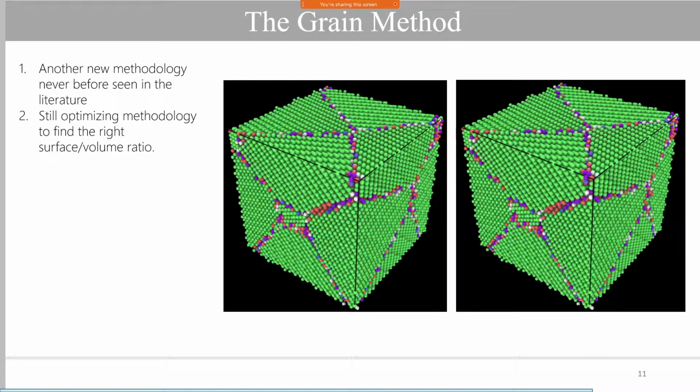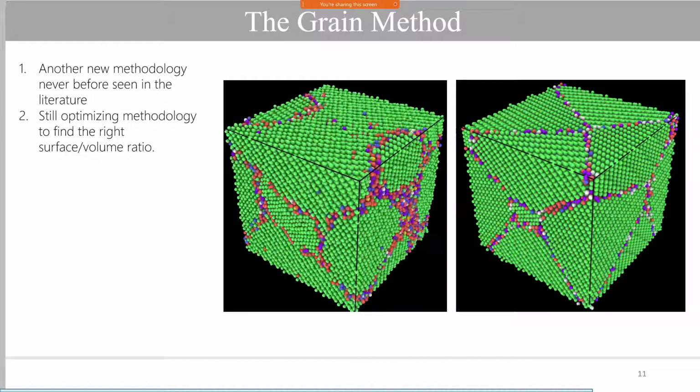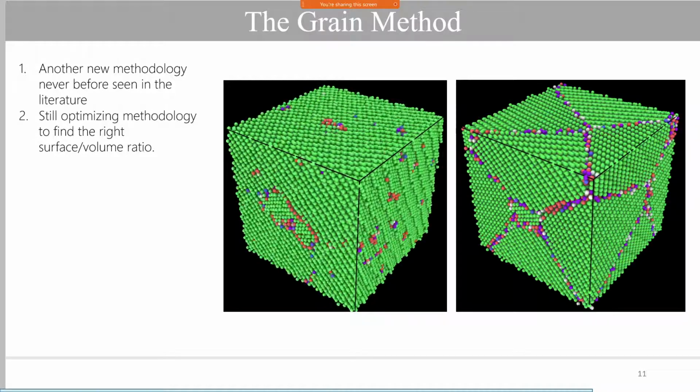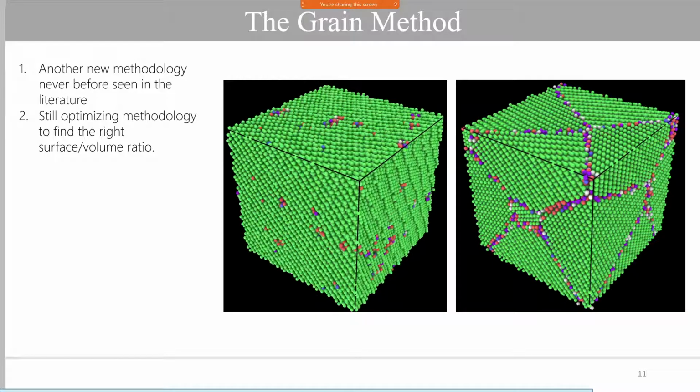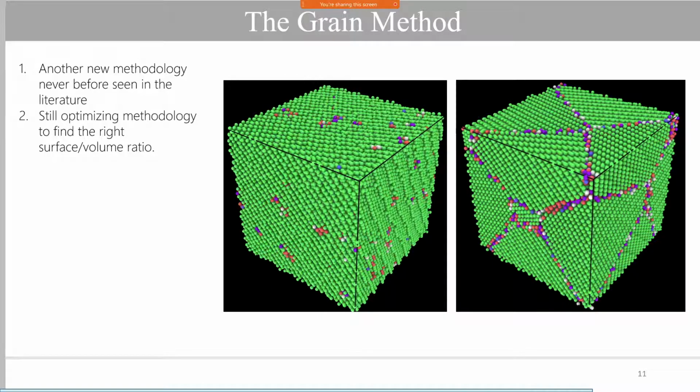Here are two example videos so you can better understand the idea behind the simulation. On the left, the simulation is below the melting temperature. Notice how the grain boundaries dissolve into the FCC lattice. The second video is above the melting temperature. Notice how, in this case, the melting starts from the grain boundaries.